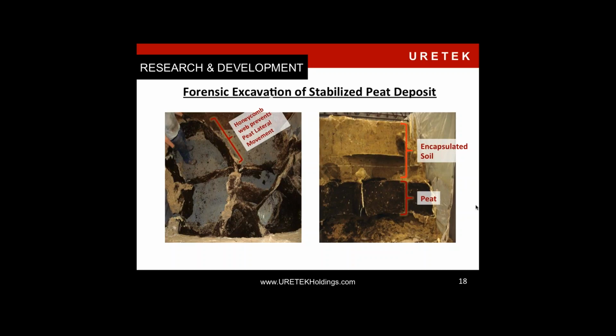The HDP material can be injected in such a way where it creates a honeycomb effect to help stabilize or support a rigid structure above. Here, in this overhead view, you can see the honeycomb structure where the HDP material was injected into the soils and created this structure. Here, the goal was not to fill the soils up 100% because of consumption of material, but to strategically inject the material to be able to achieve the goal of supporting a rigid structure above.